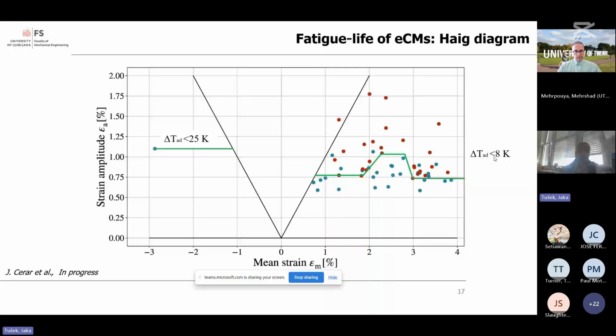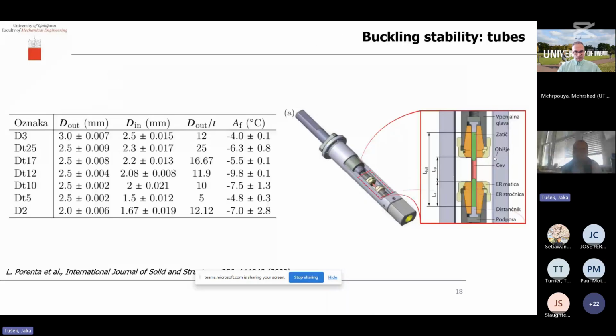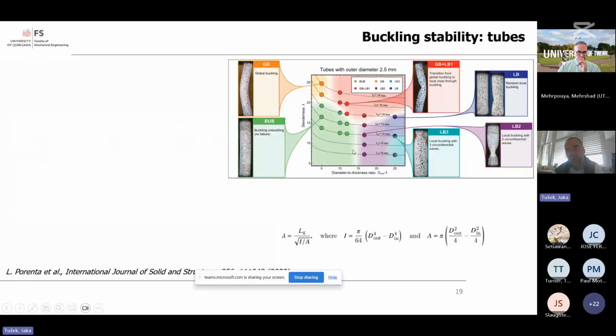Okay, since tubes show to be fatigue resistant in compression, we then also studied very comprehensively buckling stability. We tested different tubes with different outer diameters and different inner diameters, and we constructed this, let's say, buckling phase diagram, which shows different buckling modes of different tubes. Here we show slenderness, which is essentially the dimensionless length of the tube, as a function of the diameter to thickness ratio, and we are now able to detect the different buckling modes.